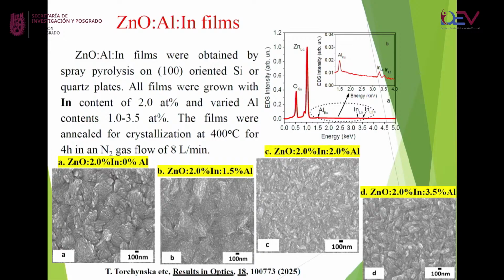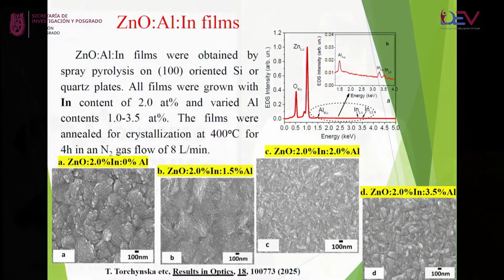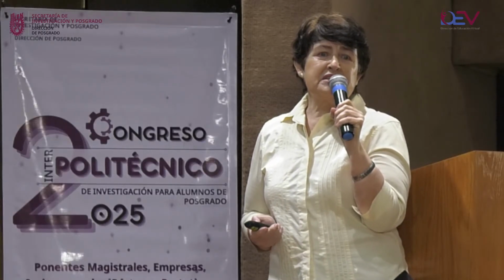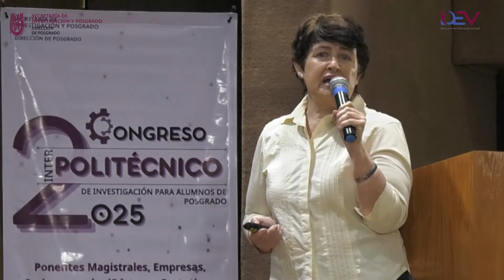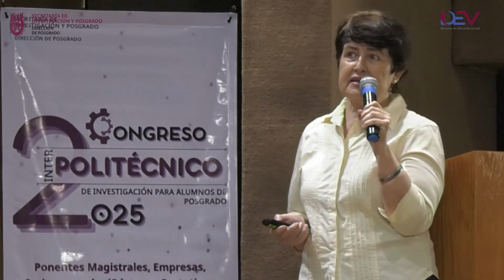You could see here SEM images of the layer that we investigated, and here you could see EDS spectra which show what elements there really are in our structure. This is zinc oxide. You could see the zinc peak, the oxygen peak, and also the aluminium and indium peaks. So we have a higher quality structure for investigation. I would like to say thanks to Dr. Ibrahim, Escuela UPIITA, which has this technology to produce such very high quality layers.